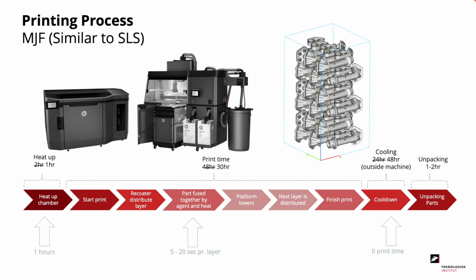Now let's have a closer look at the printing process. This is often compared to SLS because you want to have a high throughput of parts. So the time it takes to heat up is typically a little shorter for multi-jet fusion than for SLS. Similarly, the print time is also a little bit shorter for multi-jet fusion than SLS. The real gain of multi-jet fusion is in the cooling step. Here the SLS machine has to cool down some of the time within the machine, while the multi-jet fusion can cool down the whole cooling down time outside the machine. This means that you can print the next build job right after you finish the first build job.